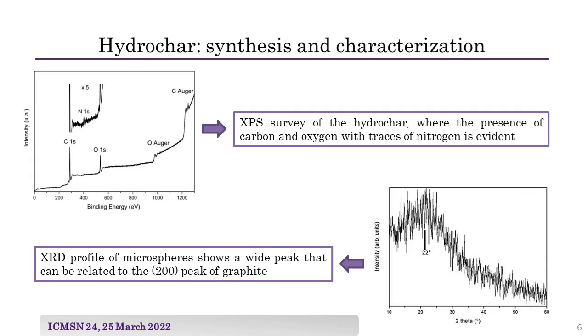The X-ray spectroscopy analysis shows that the carbonization process gave rise to a material made mainly of carbon and oxygen with some nitrogen. Also, the spectrum shows no traces of other impurities. And the X-ray diffraction indicates that the microspheres contain partially graphitized particles. The width of the 200 peak, centered at about 22 degrees, is very likely due to a wide range of independent distances, higher with respect to graphite, in which the peak is centered at about 27 degrees.